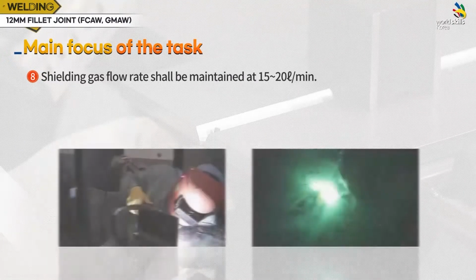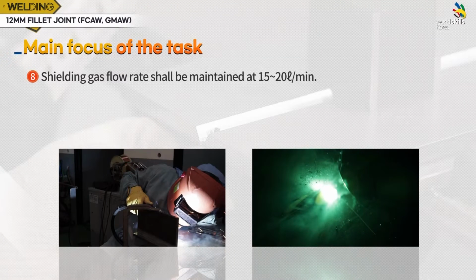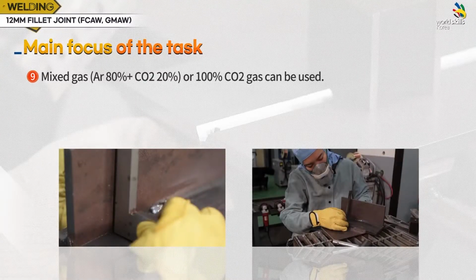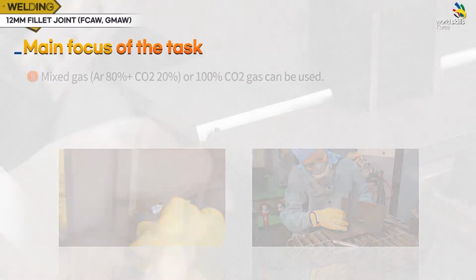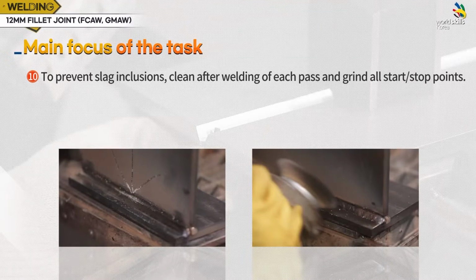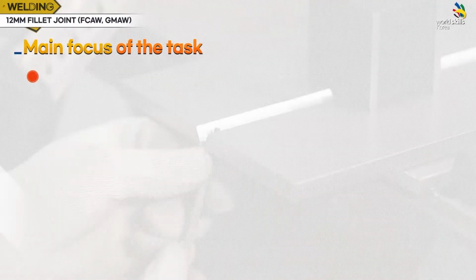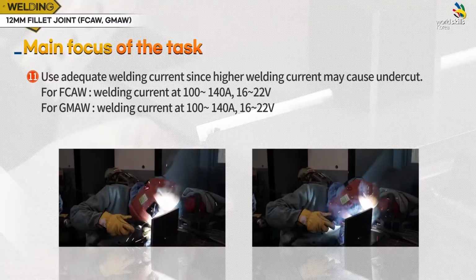Shielding gas flow rate shall be maintained at 15 to 20 liters per minute. For shielding gas, mixed gas, argon 80% and carbon dioxide 20%, or 100% carbon dioxide gas can be used. To prevent slag inclusions, clean after welding of each pass and grind all start-stop points. Use adequate welding current since higher welding current may cause undercut.